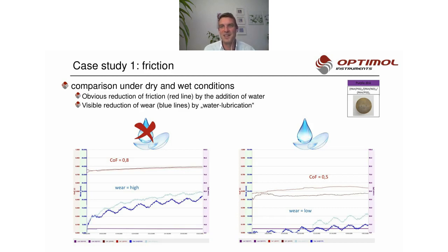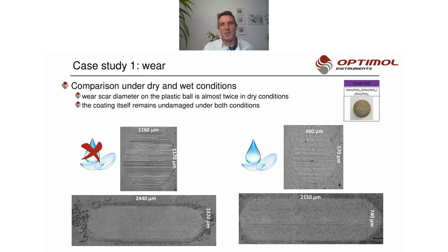And on the right side, you can see the testing procedure with this coating in touch with water. And you see a clear decrease in friction as well as close to zero wear. So this coating, this candidate, works very well for the task. I will come along with the wear situation, because it's very easy to set them into the test rig and to demount the tested parts. You can move on to the microscope and have a look at the worn parts. On the left side, this is the wear scar on the ball, and on the bottom there's the wear scar on the coated disc.